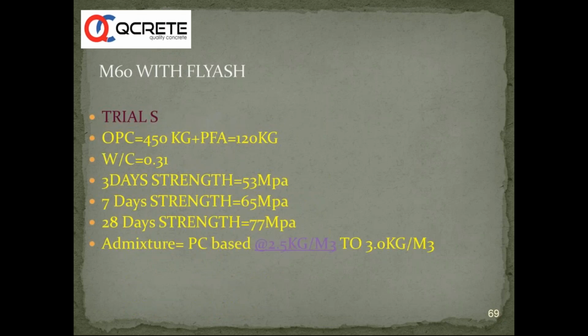So we also tried for a customer OPC fly ash mix for high grade concrete, because the customer had come up with the hesitation and telling that no, you cannot get a M60 concrete by using fly ash. So we took it as a challenge. We made trials and we supplied about 30 to 40 cubic meter of this concrete way back in around 2008, 2009 actually, for a particular customer in Hyderabad.